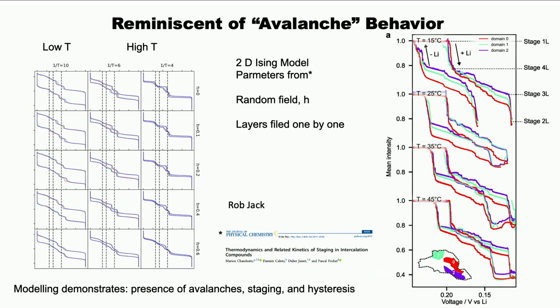And this is reminiscent of something called avalanche behavior, which you all know what an avalanche is. Something goes and it suddenly goes, and it's associated with the sort of pinning in the layers. And then once you've overcome that activation barrier, then the whole thing goes, and you get these types of characteristic phase transitions. So it's interesting, it's a totally different mechanism for graphite that, despite this material having been worked on for many, many years, hasn't been seen before.